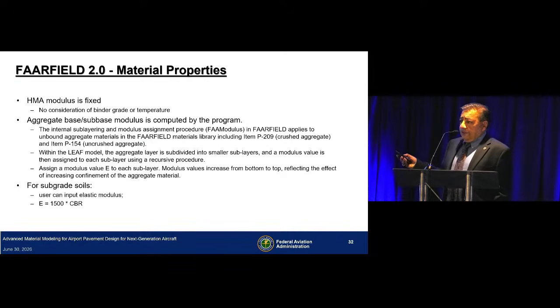To summarize the table, what you find is that the modulus of asphalt concrete is fixed at 200,000 psi. So it does not matter what binder grade you are using or what temperature it is, the modulus is fixed. For aggregate and subbase, the modulus is computed by a routine embedded in FAARFIELD, and it looks at internal sublayering and then assigns modulus values, with modulus increasing from bottom to top, and that sort of accounts for the confinement, because confinement reduces as you go down in the pavement structure.